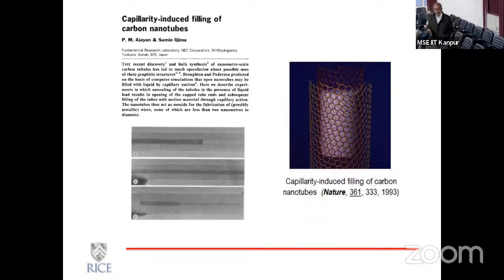So the idea was that I was playing around with this carbon nanotube and some metals, particularly to increase contrast, because if you deposit some metals, you can get better contrast to image. And then you did some annealing. And one day when I was looking at these samples, I saw that the metal, and again, I used whatever metal was available, which was lead, melted during this annealing process. And not only did it spread on the surface, but it actually got into the channels of the nanotube. So we called it the filling, capillary filling.